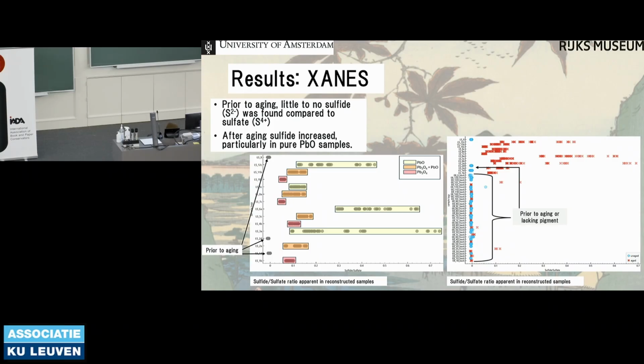So these graphs essentially chart out the ratio of sulfide to sulfate. And here you can see that these are all the samples with pigment on them. And you can see that these are unaged or have no pigment. And once you age it, the amount of sulfide jumps up. This graph is essentially a zoom in of this portion of the graph and is illustrating that while the samples with red lead do have an increase in sulfide, the samples with pure lead monoxide have a much greater increase in lead sulfide after aging.